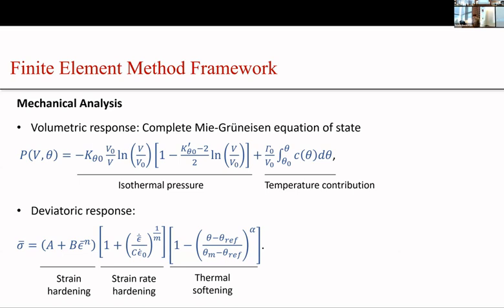I would like to mention that all the parameters are fixed during the simulation, for all the experiments, except for the rate sensitivity coefficient M. We have taken the rate sensitivity to decrease as pressure increases, so that we can capture the wave profile better. And the M in our simulation goes from 4 to 2 as the pressure increases to 100 GPa.